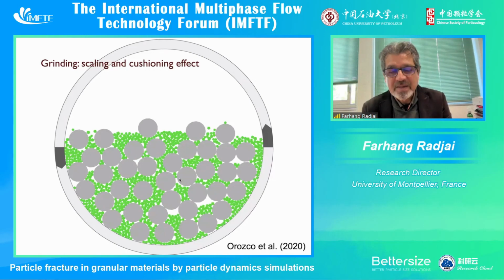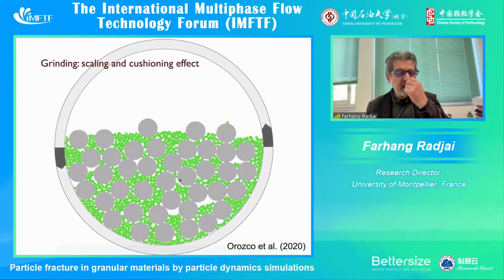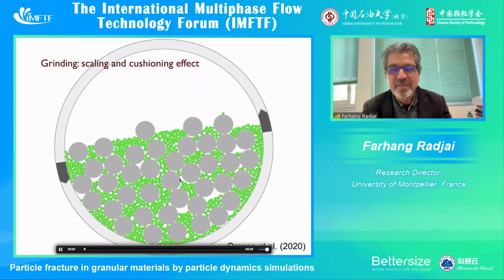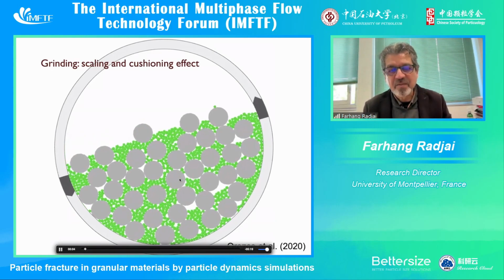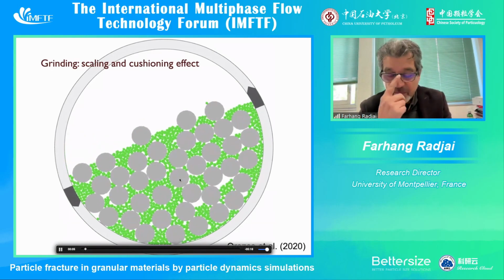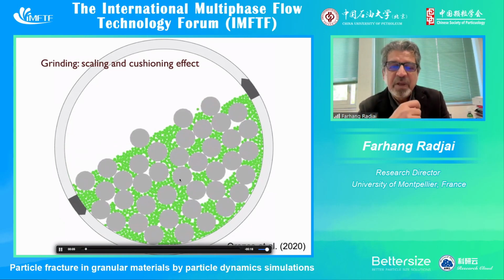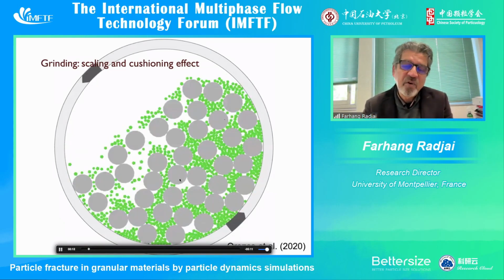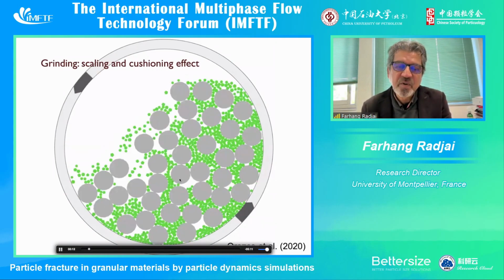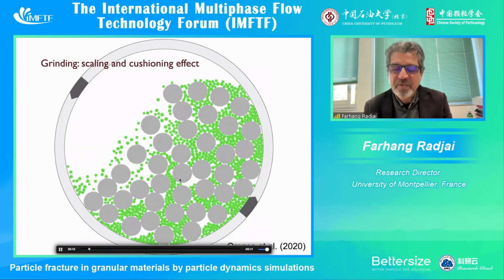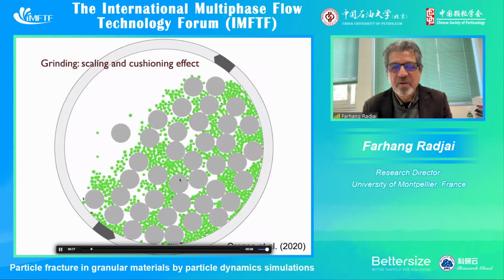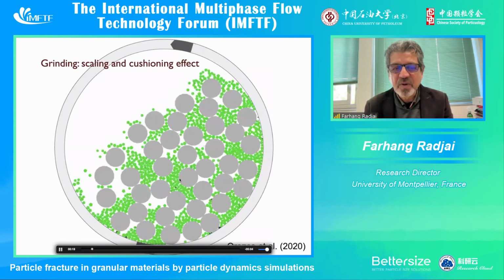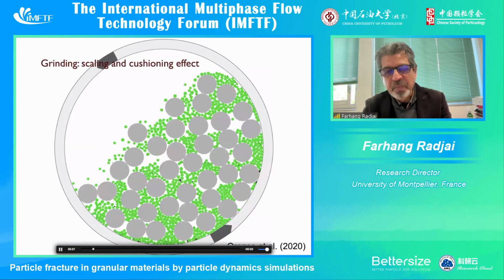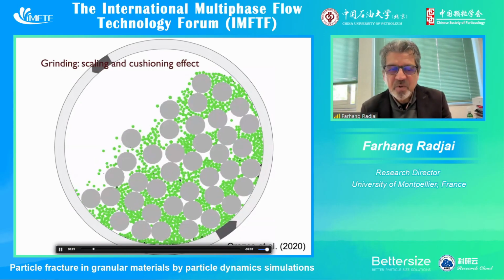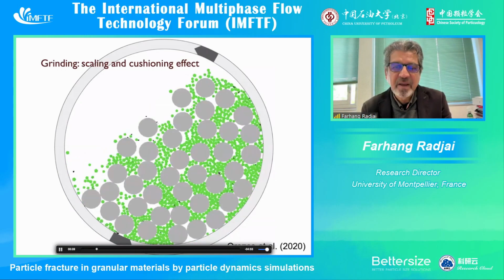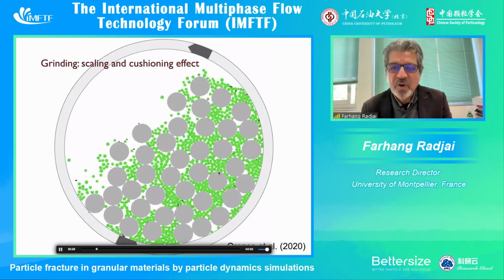So as I told you, we use what we call bonded cell method. Here is an example of simulations of a ball mill in which we use this Voronoi tessellation to transform particles into an assembly of fragments. And then we use fracture mechanics to break the particles. And as you see here, the particles which are broken are colored in black. And as it is rotating, we get more and more.